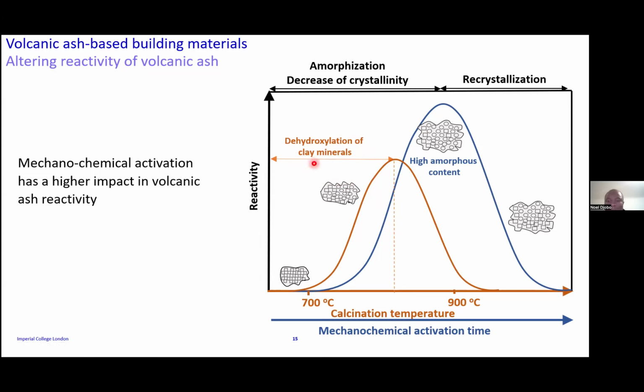But since in many of the volcanic ash, the clay minerals are available in very low percentage, like less than 2-3%, calcination is not efficient. So one of our work rely on the mechanochemical activation. The process is you induce a chemical reaction by a mechanical process. So when you put volcanic ash in a ball mill, when the milling is happening, you have a process we call amorphization, which means the minerals present in volcanic ash will be destroyed.